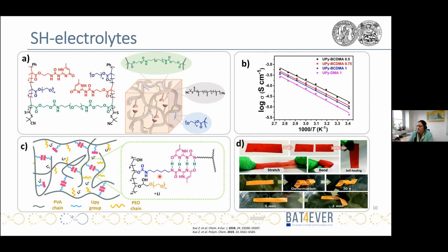Another interesting example with the UPy group is presented here. This is a self-healing and also shape memory solid polymer electrolyte, where we have again the polyethylene glycol side chain and the UPy groups, but here we have polyvinyl alcohol as the basic polymer. The polyvinyl alcohol features numerous properties which make them promising candidates as a polymer matrix for solid polymer electrolytes. They have good thermal and mechanical properties. They are non-toxic, exhibit a relatively high dielectric constant, and a good film forming property.